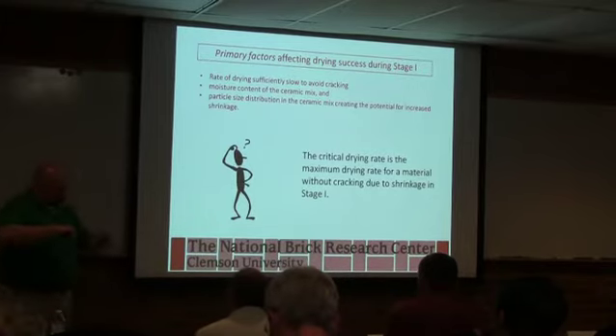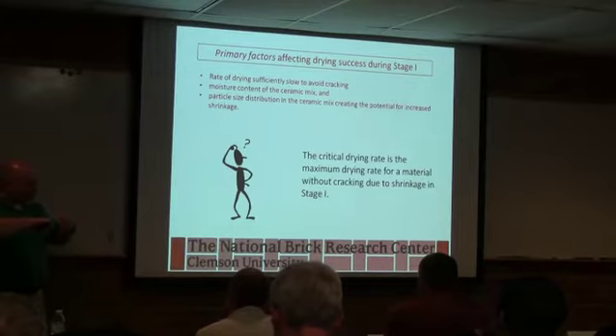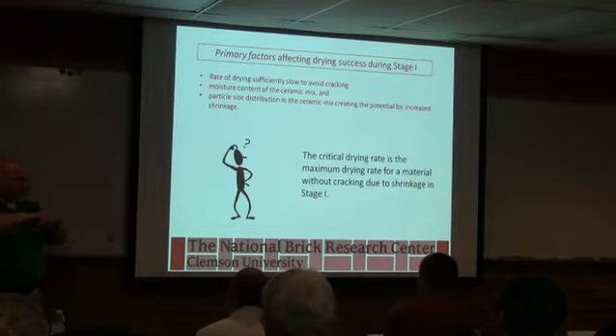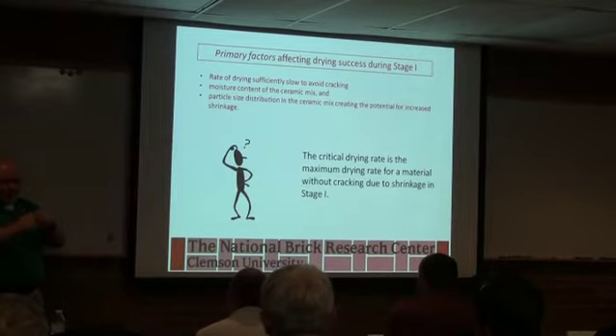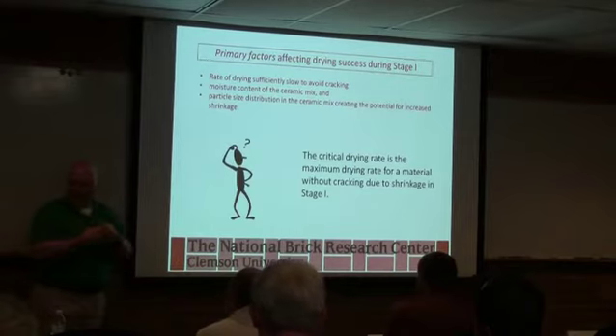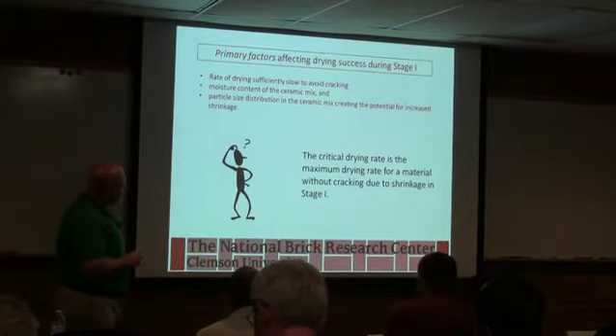And the way I've always thought about it is, if I've got two particles coming together, there's a water film between them, and I go very fast, they hit, and they may not be in the most beneficial orientation to each other. Okay, so they just bump into each other real quick. But if I'm drying slow, they can orient, and they can come to a lower stress state where they're happier next to each other, and you end up getting a slightly higher shrinkage.